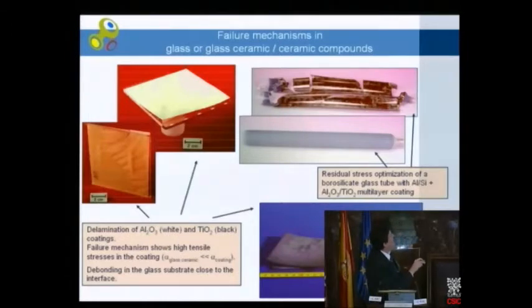An extreme example is shown here. This is a so-called ozonizer tube. That was a precision glass tube with a metal electrode and a ceramic dielectric on top. And this is the same product, a little bit different magnification. That's how it looks. A borosilicate glass as a carrier, and this double layer in a situation with well-balanced residual stress distributions. And this can happen if you leave for lunch in the morning, your piece looks beautiful, and you come back and you think, oh, some foe has destroyed my sample. It was just the critical amount of residual stresses that bring the piece to something like an explosion.